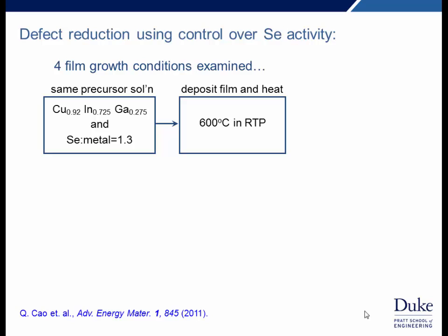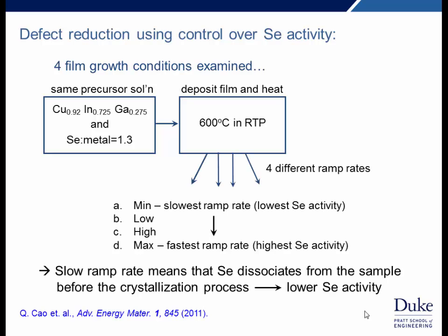So introduction of impurities is one powerful technique for improving device performance. Another approach that we've explored is control over the thermal processing. In this experiment, we have the same starting solution, same metal composition, same excess of selenium. We're processing to the same final temperature in a rapid thermal annealing tool, but we vary the heating rates from minimum to maximum.